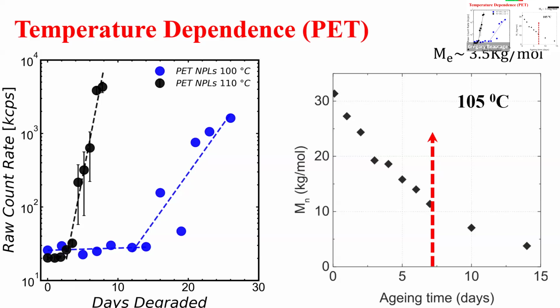You going to say something? So is this worse in India than in Canada, where you have the average temperature difference? India probably spends more time at 30 to 35 degrees. Things are happening. Anytime it's hotter, you can see here, 10 degrees changed the whole thing by about a factor of 5. So with 20 degrees, it's going to be an order of magnitude. Yeah, look to India, you see the future. Yeah, that's another nice way of saying it. Look to the Indians.